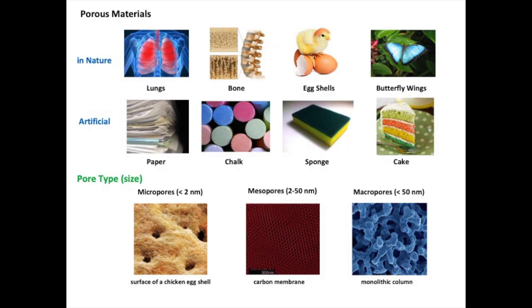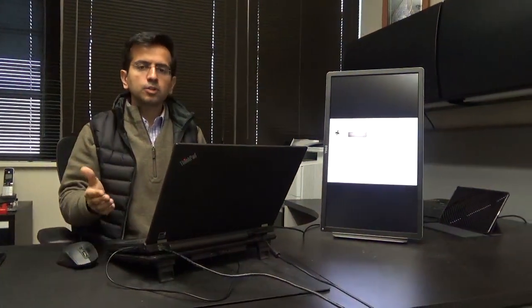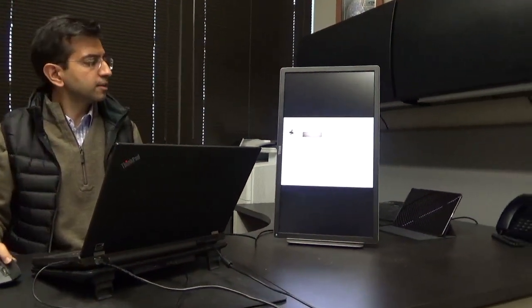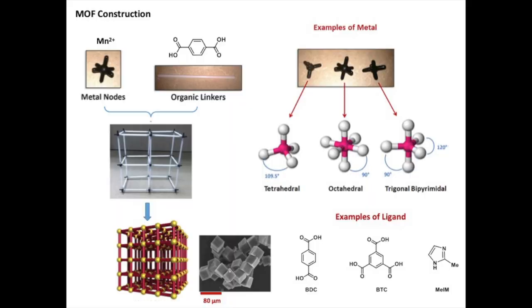So basically, the way that we make these hybrid materials to make extended networks using molecular structures would be to use a metal system, like in this case a manganese 2 metal as the inorganic side, as well as an organic linker, which we also call struts. We basically mix these two together, and in this case we have a linear linker, benzene dicarboxylate, and we would essentially make this cubic structure.